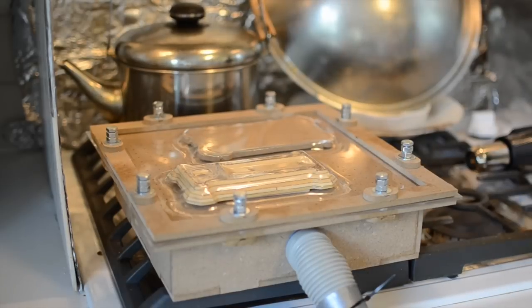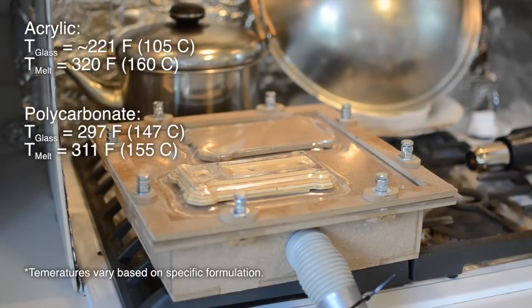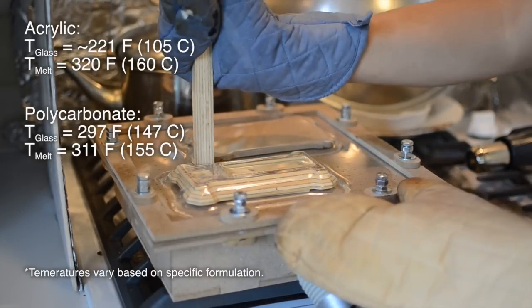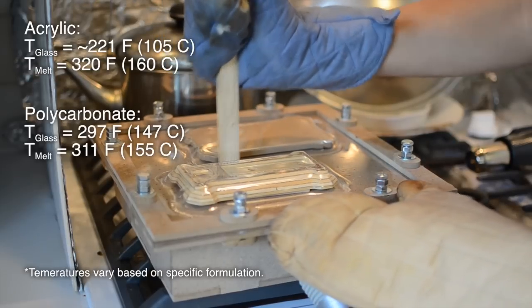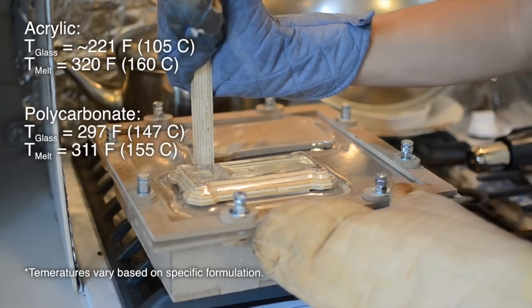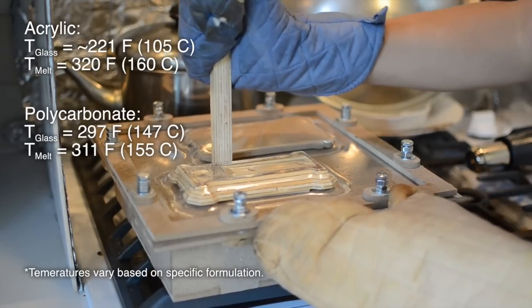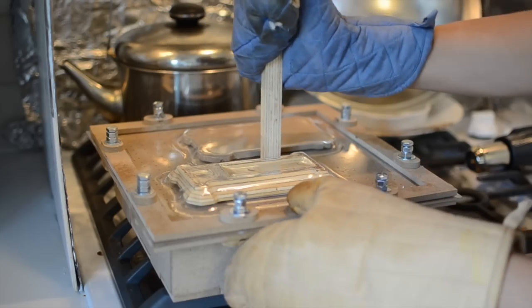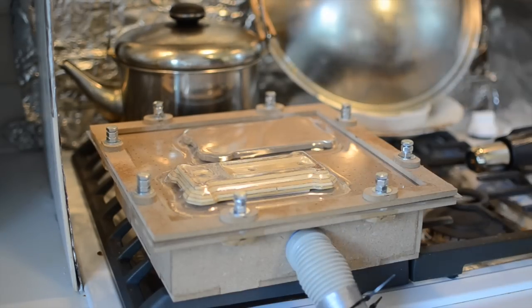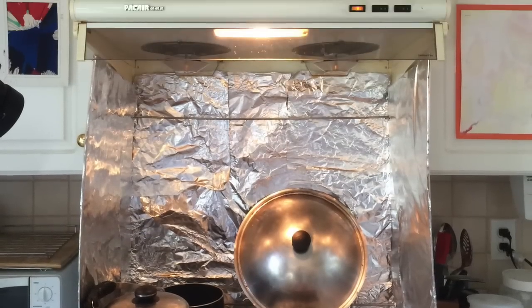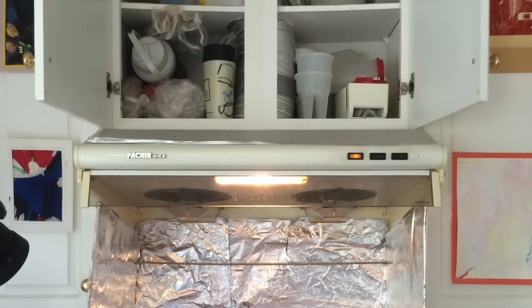Acrylic, in the thickness that I'd chosen, is pretty difficult to work with. Even when it's brought past its glass transition temperature, it has a finite bend radius that you can't exceed unless you get much closer to its full-on melting point, and I wasn't comfortable doing that in my oven. I considered moving the entire vacuum table and mold into the oven and slumping my plexiglass over it at 400 degrees, but I figured I'd keep the hot working to my stovetop, which has a range hood that actually exhausts to the outside of the house.